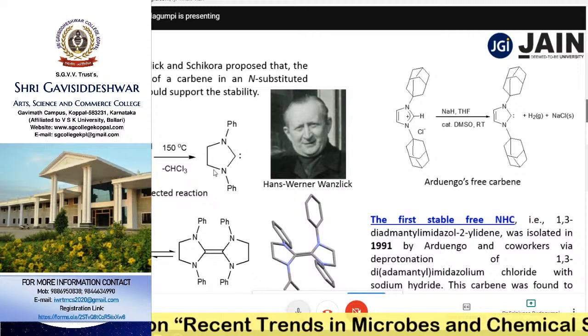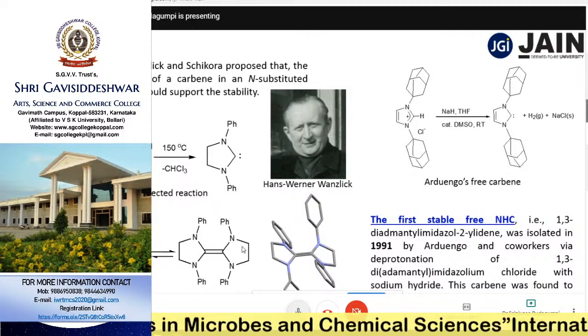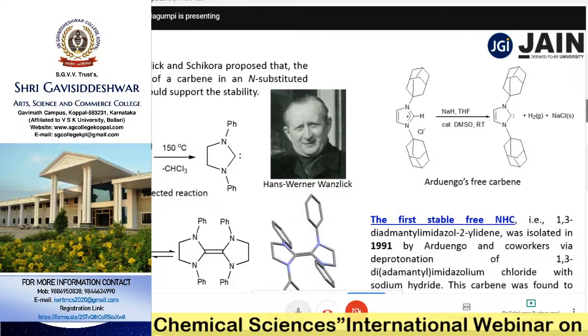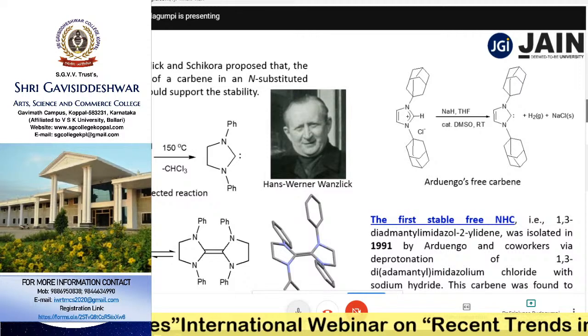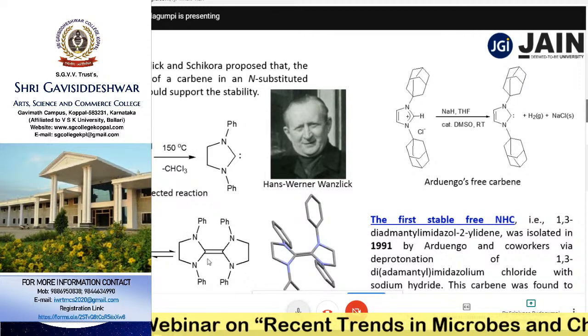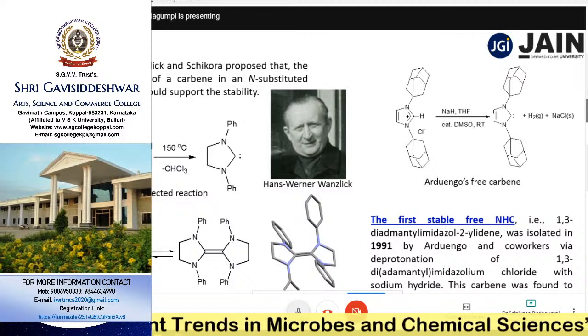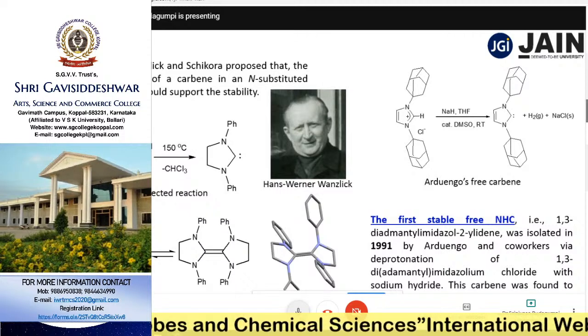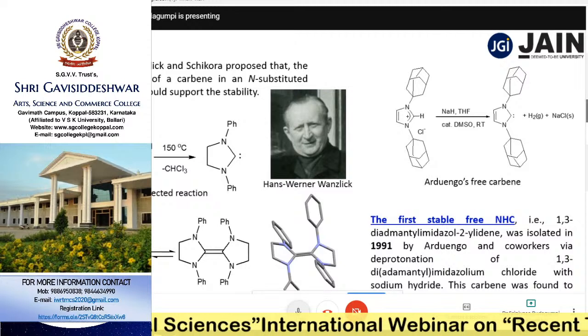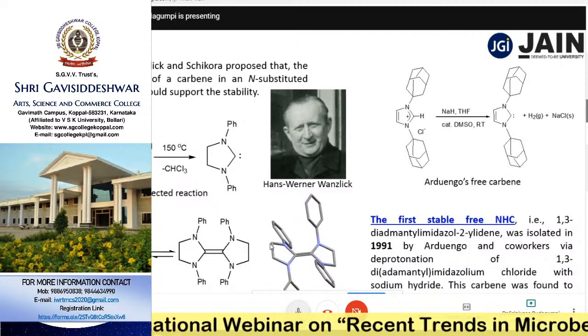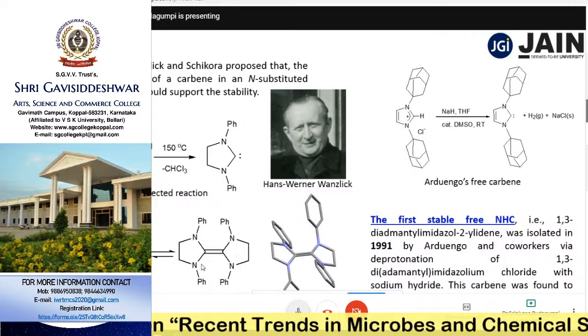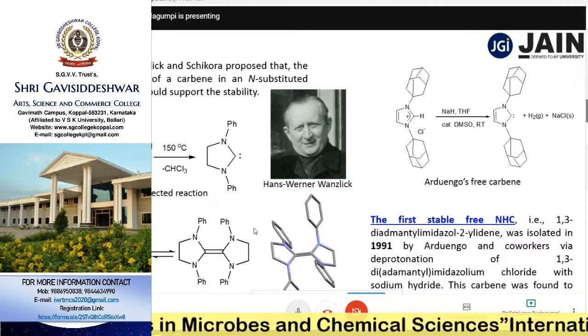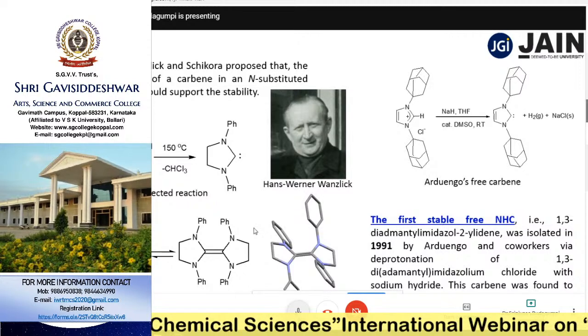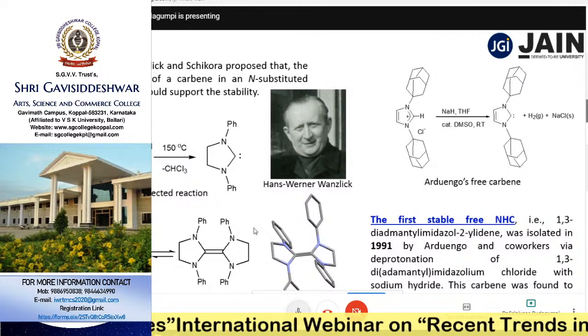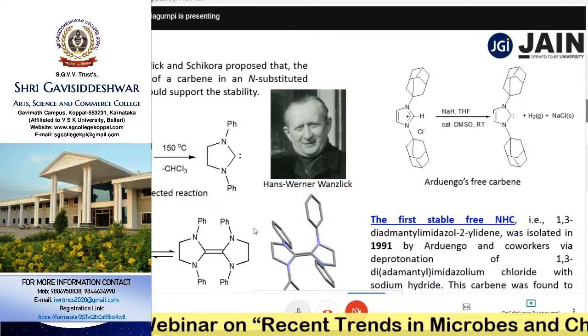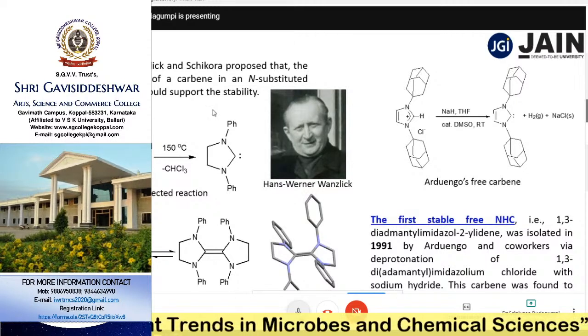Unfortunately, that eventually led to the formation of a dimer. Two of these carbenes dimerized to form this kind of dimer, and this dimer is in equilibrium with the carbene, but it is not 100% pure carbene. The carbenes are in equilibrium with the dimerized product in this way, and this equilibrium is called Wanzlick's equilibrium. Isolation of the free carbene was unsuccessful until Arduengo's free carbene isolation in 1991.